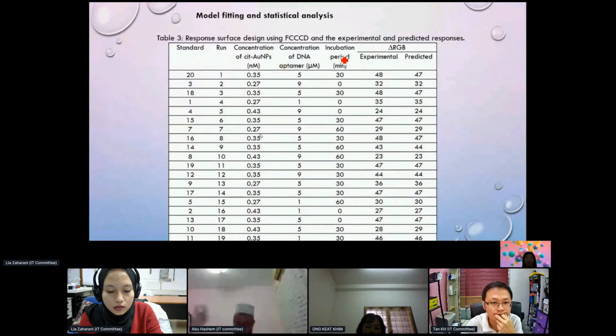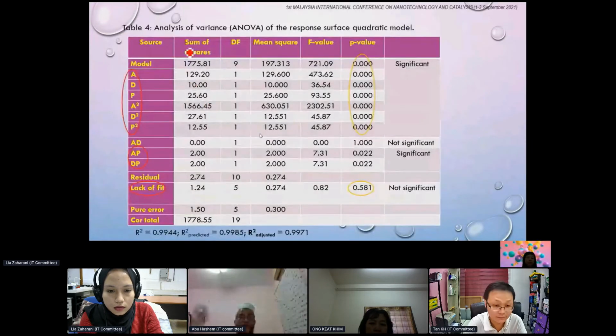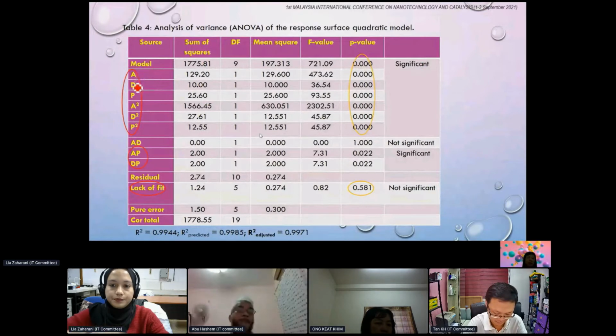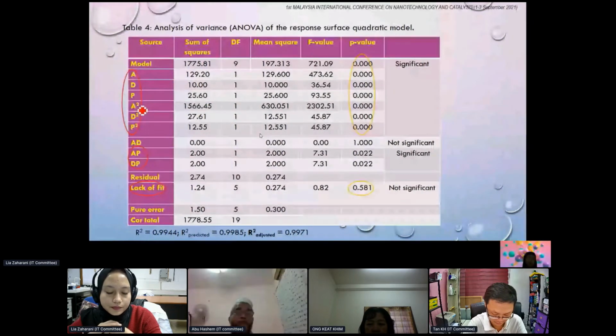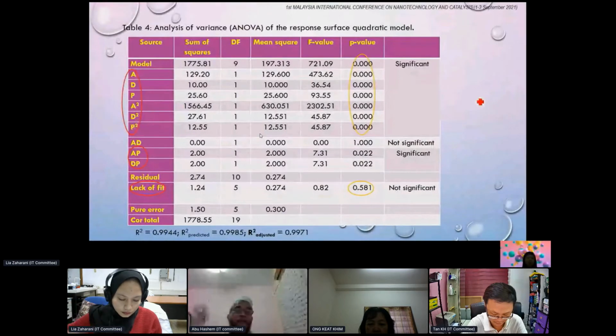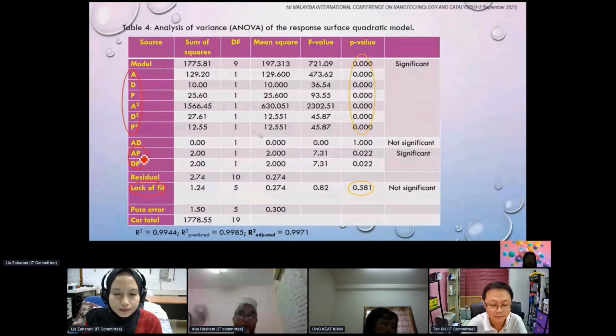Table 3 shows the experimental and predicted response as shown in this column. The result of ANOVA is presented in this slide. So you can see the model is significant. Factors A, D, P, A power 2, D power 2, and P power 2 are significant. Interaction effects between A and P, and D and P are also significant. However, lack of fit is not significant, showing that the model can predict the response very well. In addition, the R square is also high as shown here.